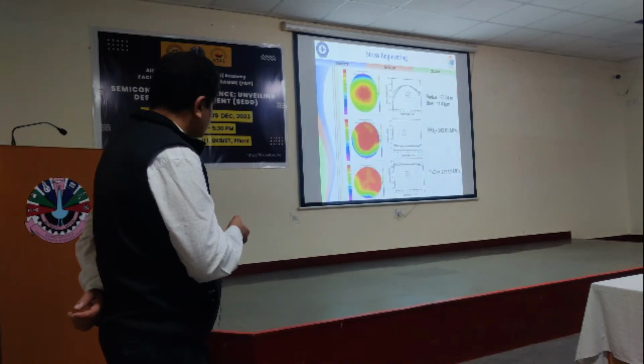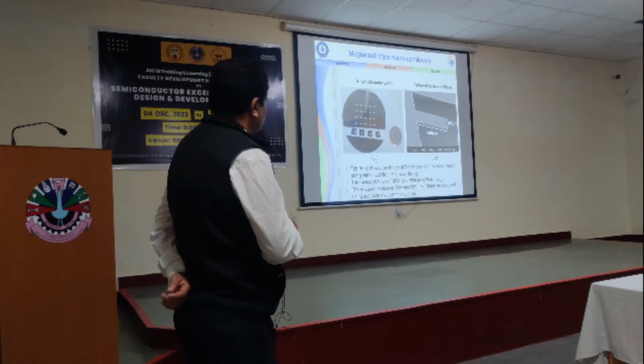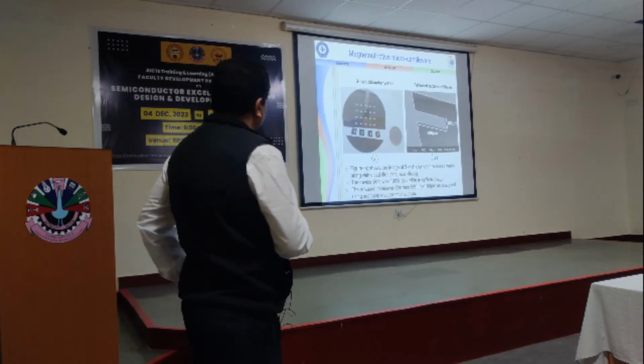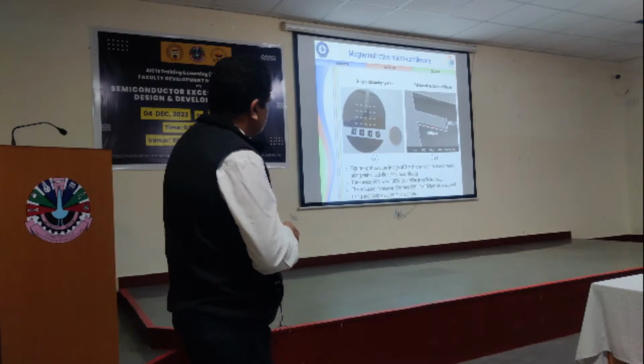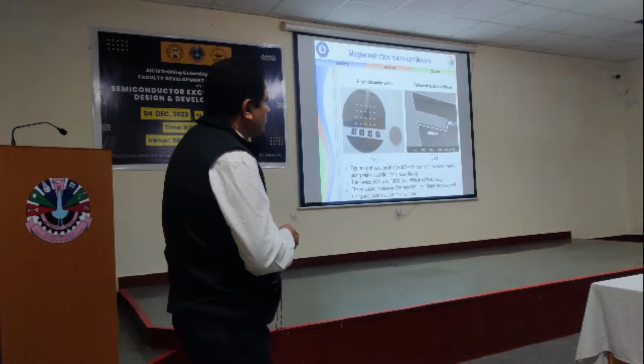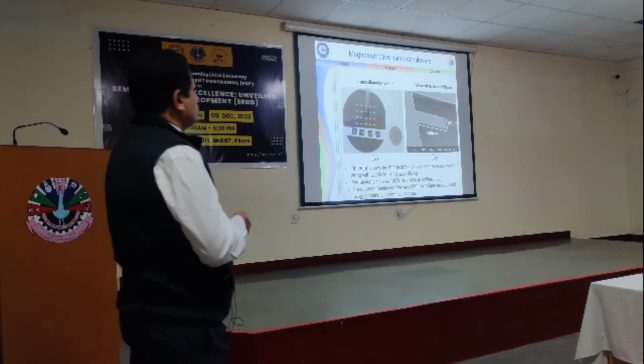Similarly for these you can see here the wafers, 3-inch wafers, and these cantilevers are made on it, and one die you can see near the coin. So it is so small, smaller than this dimension. And if you measure these cantilevers, this cantilever width is 500 micron, means 0.5 mm, length is 0.1 mm. So very small size micro cantilevers are made and used for the magnetic sensing applications.